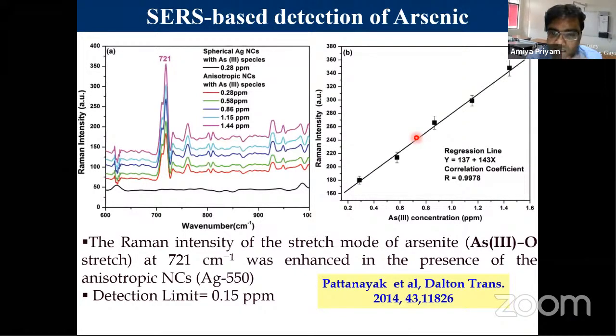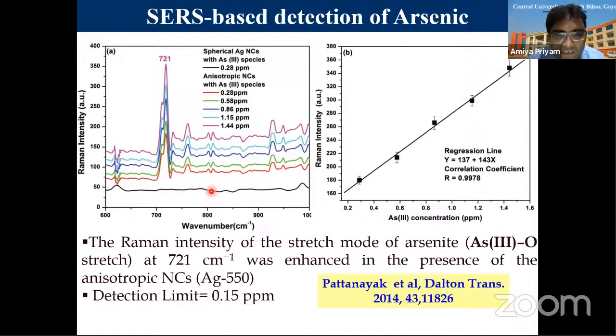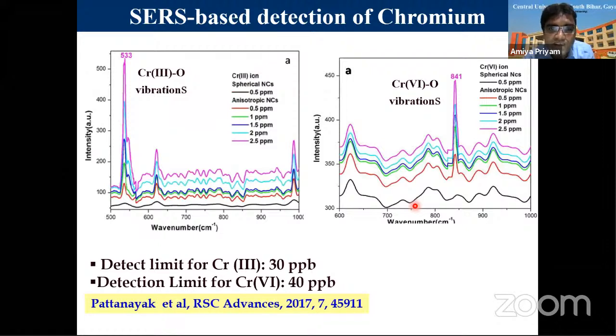By using these anisotropic, pyramid-shaped nanoparticles, we were able to develop a method for detection of arsenic in water. This is the method which we call surface enhanced Raman scattering. You can see here, in case of simple arsenic in the water, we are not seeing any peak, but when we add nanoparticles, we are getting an intense peak over here. And when we plot it with different concentrations, this is our calibration curve. Similarly, chromium 6 and chromium 3 present in water can also be analyzed. And the lowest detection limit is 30 ppb, 40 ppb, and so on. So these are the methods.